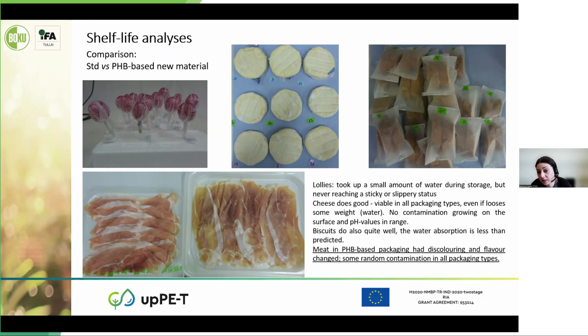Summarizing, we can say that the lollies took up a small amount of water during storage, but never reaching a sticky or slippery status, so a good result. The cheese also does good, so for this specific cheese, who has this specific breathability needs, this kind of new material is very good. Some problems which have to be eventually faced in the future about weight loss of the food product along the shelf life. No contamination growing on the surface and pH values in the range.